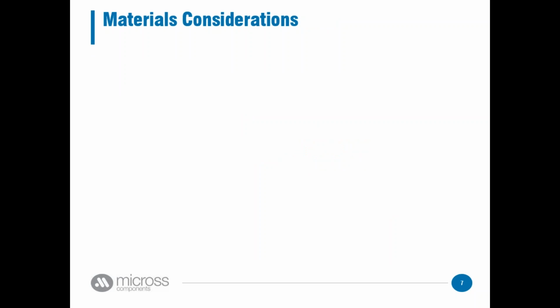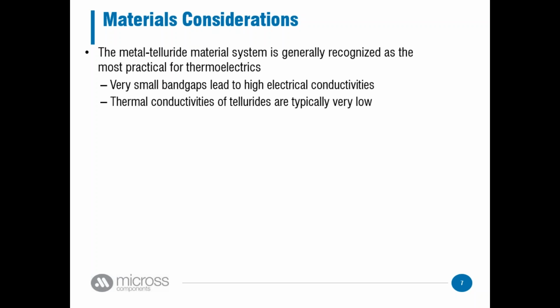For the material, like I said, finding materials is a challenge. What type of materials can you use that are going to give you not only the Seebeck, but also the high electrical conductivity and also the low thermal conductivity? Basically metal tellurides: bismuth telluride, lead telluride, germanium telluride. They're the type of materials that are generally used for thermoelectrics, the most popular and most common. That's because they have small band gaps. Their band gaps are generally less than 1.